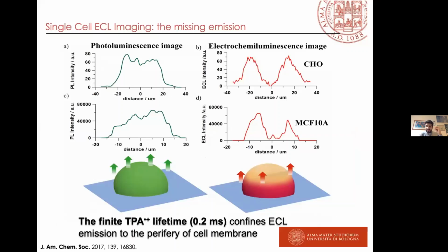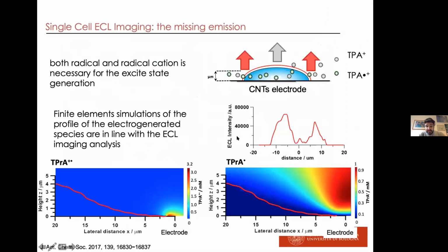So why do we have the emission only from the periphery of the cells? Because we generate the TPA radical at the electrode surface, and the TPA radical needs the deprotonation. This TPA radical has a lifetime that in this case was reported here as 0.2 millisecond, so you cannot visualize all the cells. You can visualize only the border of these cells, because the TPA radical cannot reach the very top of the cells.